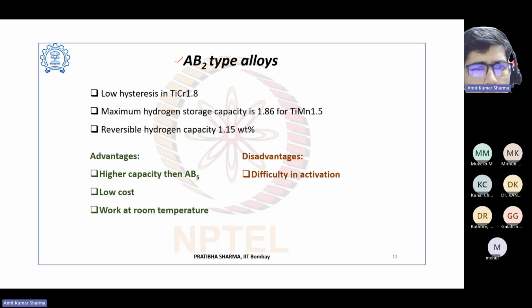For these AB2 type alloys, we have seen low hysteresis in TiCr1.8. The maximum hydrogen storage capacity, 1.86 weight%, is for TiMn1.5, and reversible hydrogen capacity is 1.15 weight%. Advantages: higher capacity than AB5, low cost. It also works at room temperature. Disadvantage: difficulty in activation.